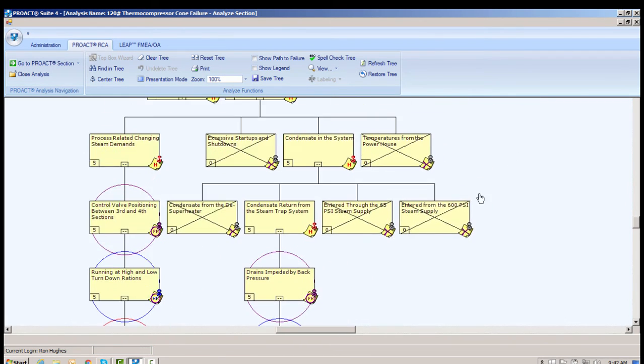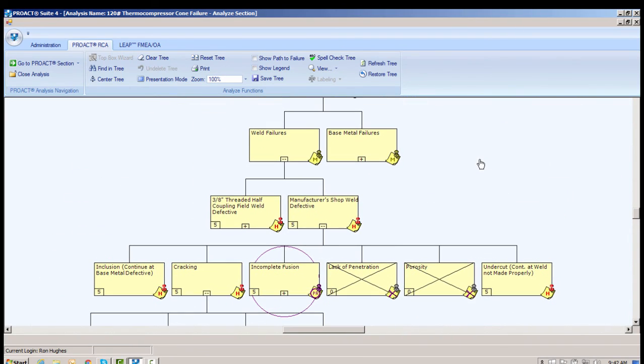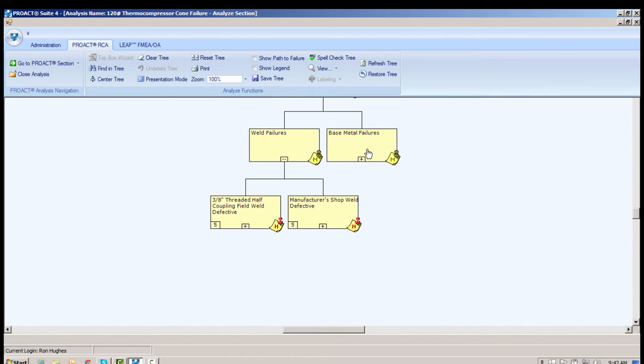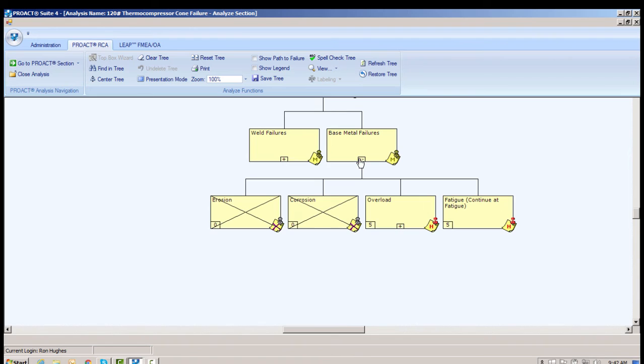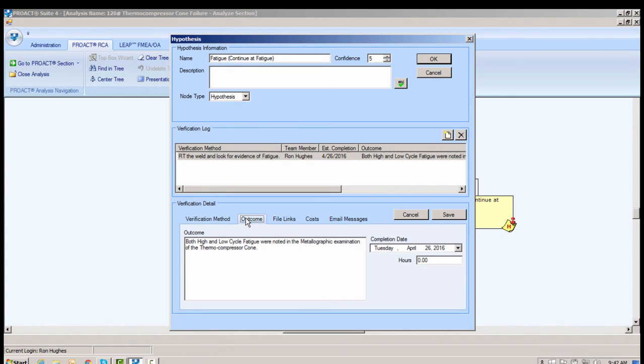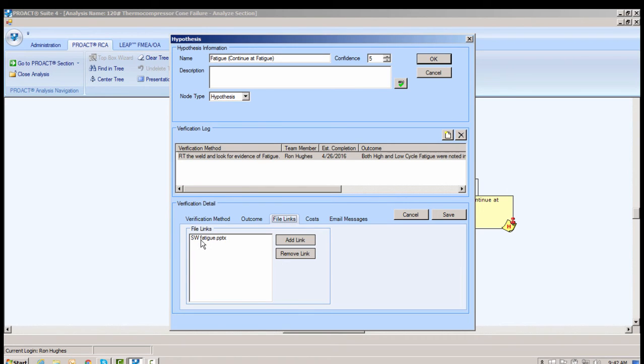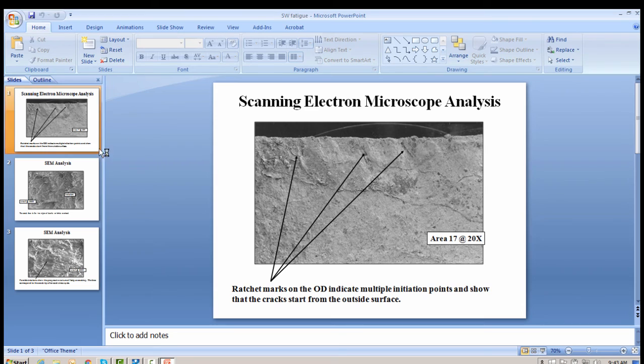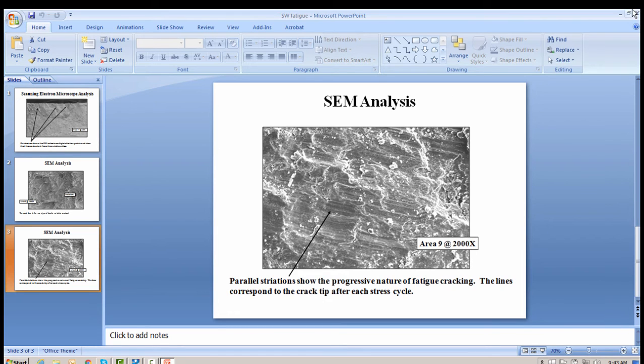Alright, let's move up here, and we're going to minimize this and go over here to base metal failures. Alright, how can I have base metal failures? Again, we're at the component level: erosion, corrosion, fatigue, and overload. Now notice over here under fatigue, we prove we have fatigue. We RT the weld. We see both signs of high and low cycle fatigue. This is the actual manufacturer's weld again. And we're back to the scanning electron microscope analysis and metallographic analysis. And we see both evidence of high and low cycle fatigue.